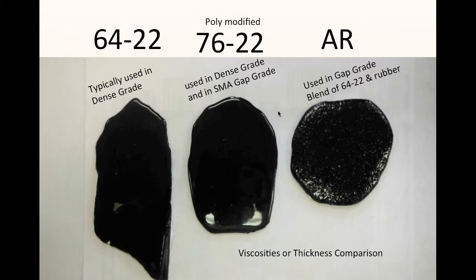That's considerably more expensive, to the tune of, if we're looking at $500 to $600 a ton for a 64-22, you can throw an extra $100 to $125 a liquid ton for the mix with the plastic asphalt in it. The asphalt rubber on the right is a blend of 64-22 and rubber, as we said, anywhere between 80-20 and 90-10. And what you're looking at is the viscosity difference or the thickness comparison. These were just basically 20-gram drops of asphalt left to sit at room temperature for a reasonable period of time, and you see kind of how far they spread out.